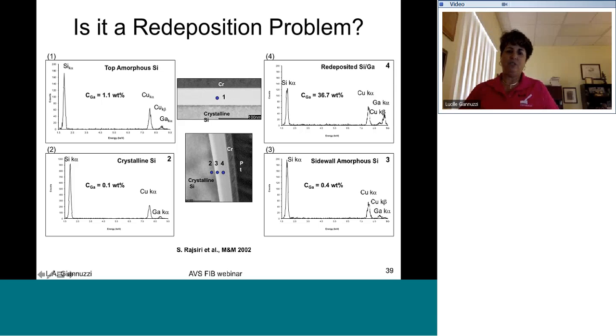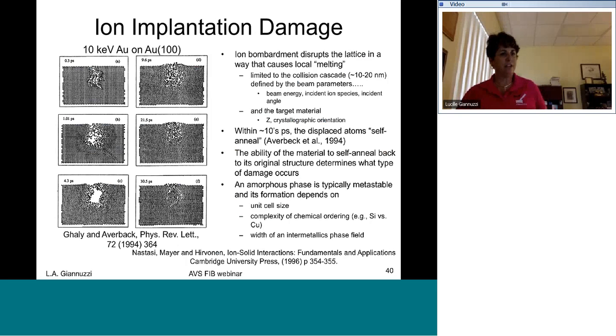This is a redeposition artifact, which is where in 3 here, that's your typical amorphization layer. So if you're seeing, again, a lot of gallium in your samples, that's a redeposition artifact, and that's not an inherent ion-solid interaction artifact. Okay, so when you ion implant, again, I mentioned earlier, you can also generate a metastable phase.